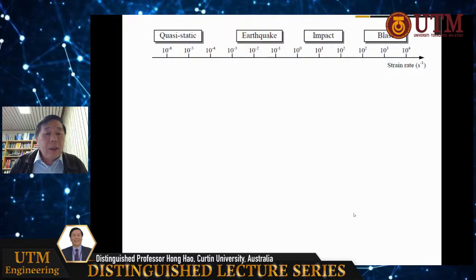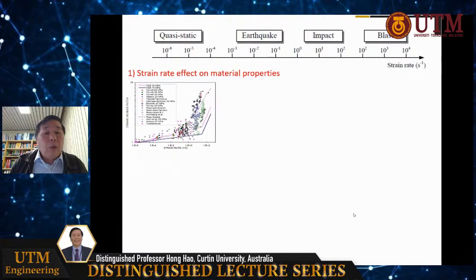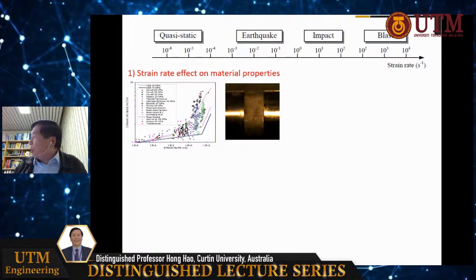One reason is the strain rate effect. Under static loading, strain rate is very, very low. We're talking about 10 to the power minus 6 strain rate. Earthquake is about, at most, about 1. And impact and blast could be very high if it goes to a compact, close-in explosion. The strain rate could be 10 to the power 4, and if you have bullet penetration, the strain rate can go to 10 to the power 5. So the strain rate will change the structure, the material properties.